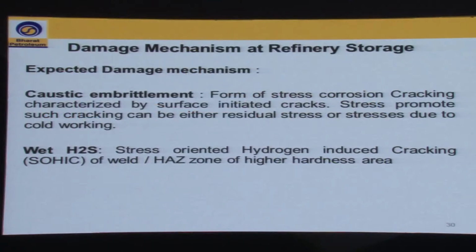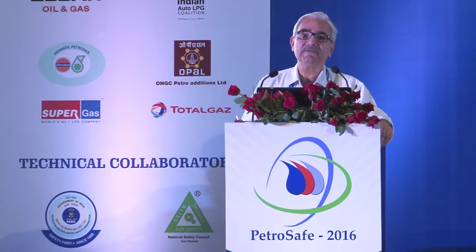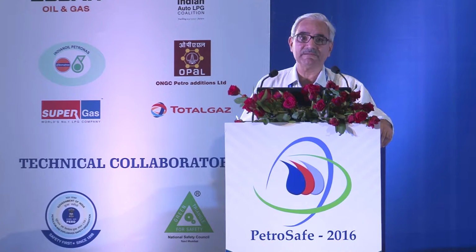Expected damage mechanism, in case of refinery mounded bullets which are attached with the refineries, is caustic embrittlement, which is a major issue, and wet H2S, because sometimes H2S is also there in the process when we are producing LPG. That wet H2S is a major source because it generates atomic hydrogen, which gives rise to cracking of the steel. So there it is very important. The post-weld heat treatment is very important to control the hardness factor. HIC or blistering damage develops without applied residual stresses, hence post-weld treatment will not prevent such damage.